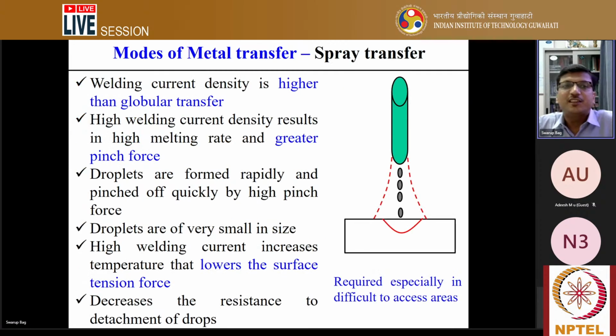Here you can see the modes of metal transfer. Specifically, I'm talking about the spray type of transfer. How does it occur? In this case, the main requirement is that the current density is very high, higher than in the globular type of metal transfer. High current density means the current per unit cross-sectional area of the electrode should be much more. So with high welding current density, the melting rate will be much more, and there is a greater pinch force, opposite to the drop holding forces. Some kind of electromagnetic force will be acting, and surface tension force will always try to hold the molten droplet, while the pinch force will try to detach the droplet.